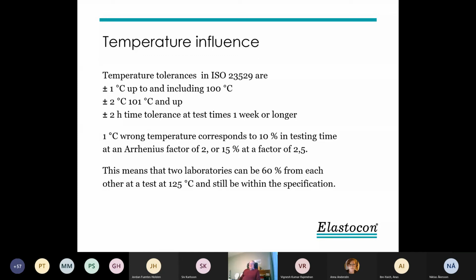But already 1 degree wrong temperature corresponds to roughly 10% in testing time, if we use the rule of thumb with an Arrhenius factor of 2. Or is the Arrhenius factor higher? It could be up to 15%. So this means that 2 labs can be quite apart and still be within the specification. That is why we later on introduced in the ISO standard the requirement of having a temperature sensor close to the samples and try to set the temperature as exact as possible where the samples are located.